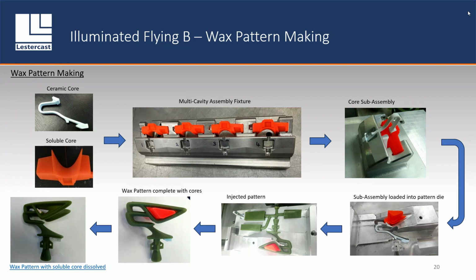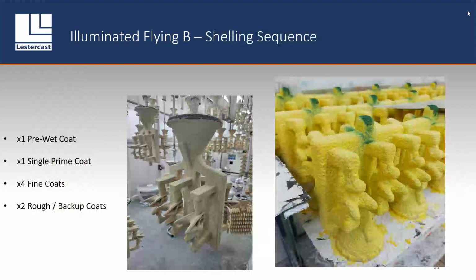And then this is a multi-cavity assembly fixture, which allows the operators to preload the soluble cores and the ceramic cores together. They can preload them, check that they fit, glue them into one another, and then put that whole assembly into the wax die, which you can see just down here. So you've got your soluble and your ceramic core placed into the aluminium die, and obviously we inject wax around it. That's the process, which is complex in itself. Again, we've not made a casting. Here is a wax that's got the soluble core removed, so you can see all the detail on the inside, and it shows you what the soluble core does in that particular case.